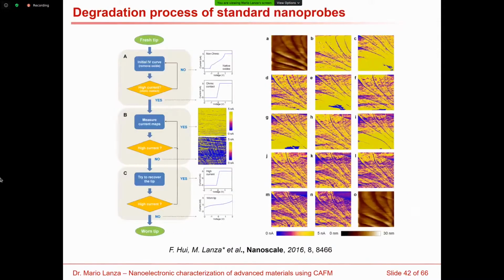So we evaluated the degradation speed of one standard conductive AFM tip. We developed one method based on an initial check of the conductivity, a sequence of current maps at a constant force and voltage, and another check of the conductivity of the tip. And we observed that for one specific tip, one specific sample, and one specific measuring conditions, our tip degrades in 13 scans. It was very obvious because initially the scans show a lot of current, which here is indicated with yellow color. And after just 13 scans, the image turns blue, which means we are not measuring enough current.